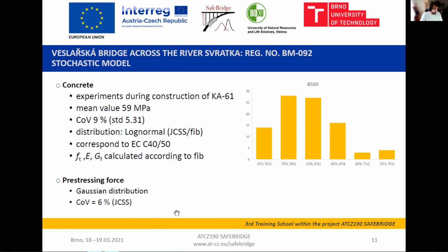Okay, the stochastic model. It's probably one of the most important parts of stochastic analysis, because if you create a really perfect model of your bridge or of your structure generally, you also need to create a stochastic model corresponding to this structure. Otherwise, it will not represent reality. So the best possible way is to obtain data from experiments, from material experiments. We are quite lucky that we obtained results of material experiments of concrete, which were performed during construction of each girder KA-61. So we statistically processed these values, and we obtained a mean value of 59 megapascals and a coefficient of variation around 9%. Then we can assume some kind of distribution.